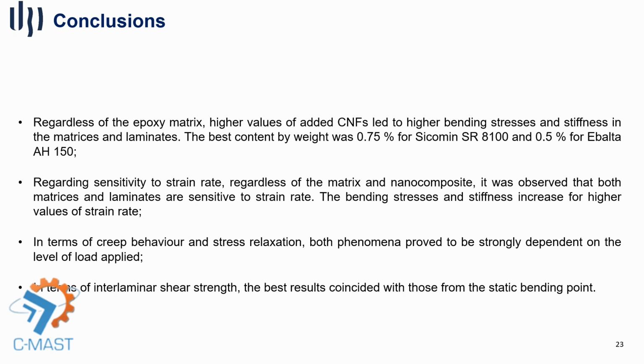Regarding sensitivity to strain rate, regardless of the matrix and nanocomposite, it was observed that both matrices and laminates are sensitive to strain rate. The bending stress and stiffness increase for higher values of strain rate. In terms of creep behavior and stress relaxation, both phenomena proved to be strongly dependent on the level of load applied. In terms of interlaminar shear strength, the best results coincide with those from the static bending point.